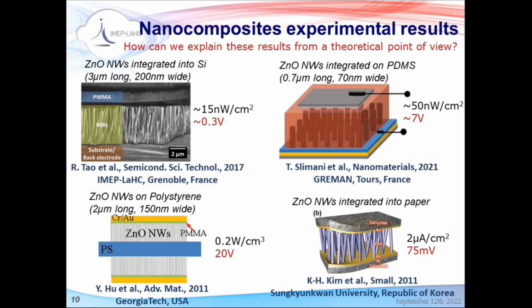But well, actually, there are many groups working experimentally in this kind of devices, in this kind of composites. What's interesting is that the nanowires you can integrate in many substrates, in rigid substrates like silicon, but also in polymers like PDMS or plastics and even paper. So there is a lot of perspectives in terms of integration. But if you take a look at these red numbers, this is the potential that they reported. So the potential obtained from these kind of devices ranges from tens of millivolts, hundreds of millivolts, even tens of volts. So actually, they work quite well. But if we don't understand how they work, then we cannot really optimize them. So how can we explain this, that these devices work?